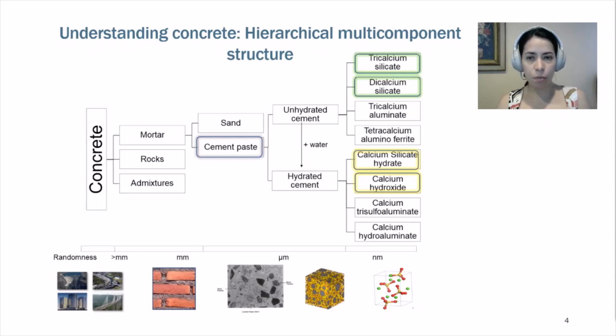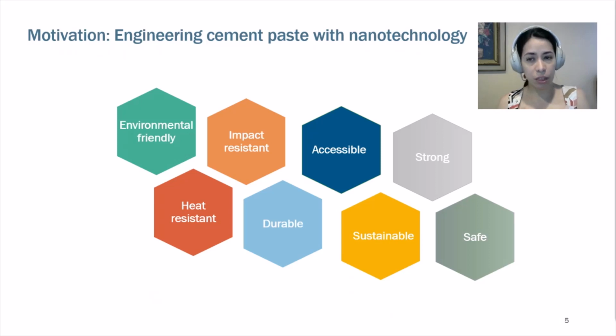Now, cement paste is a composite formed by hydrated phases and unhydrated phases that didn't fully react with water. There is also a lot of porosity in this mixture, but each of these phases, the unhydrated cement and the hydrated cement, have also other phases if we keep going down in scale at the nanometer scale. So knowing this basic initial information, we want to tailor the material. We want to make it more sustainable, but also increase mechanical and thermal properties, make it heat resistant, more durable, more accessible, etc. So to do that, we need to understand better the material at molecular level.